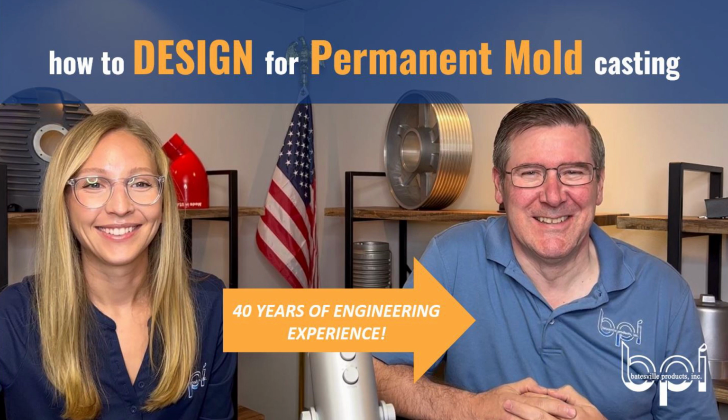So can you tell us a little bit about wall thickness and why that's important for permanent mold casting? Well, it's really one of the most crucial parts of the casting process, the wall thickness that you're solidifying, because that really defines how long the solidification is going to take. And if you have a heavy section right next to a very thin section, that thin section could freeze off and not permit the proper liquid metal fill before the solidification occurs. So you want to have gradual transitions between section thicknesses wherever possible. That's definitely one of the rules: avoid those isolated thin or thick sections.